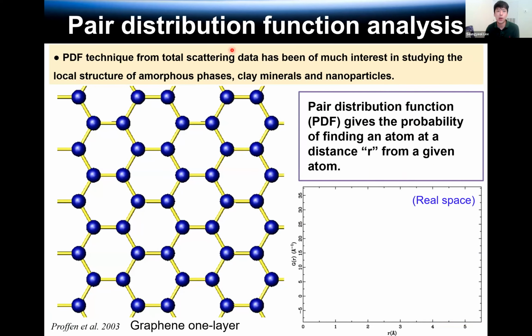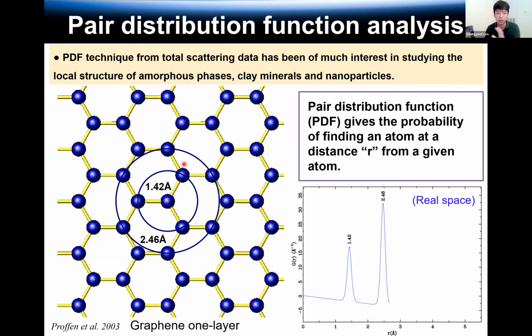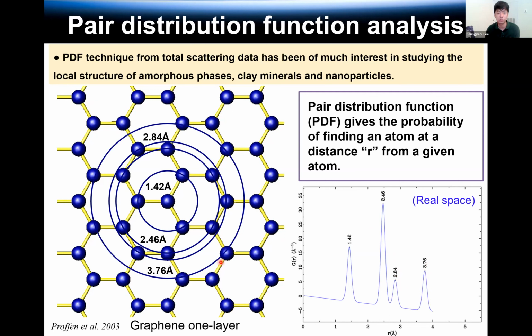Now, the third method is pair distribution function analysis. This method is quite new in the earth and planetary science field. This method simply shows the atom to atom distance. This is a graphene one layer structure. If we analyze this graphene one layer by the PDF method, the first peak relates to the first pair of carbon atoms. The second peak is related to the second pair of carbon distance, and the intensity is proportional to the number of atom pairs. The third peak is the third pairs, and the fourth peak is the fourth pairs.